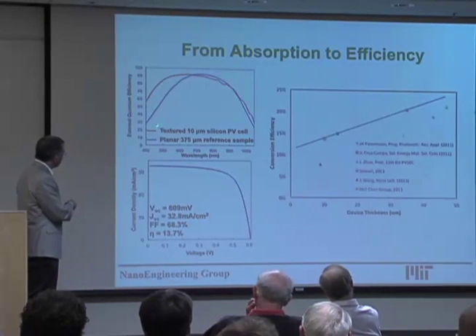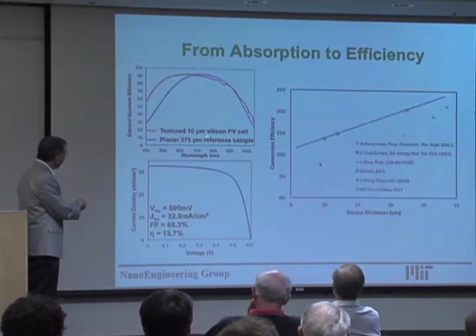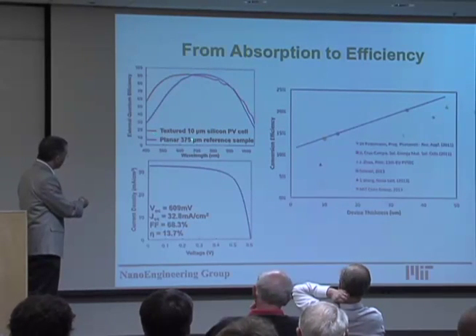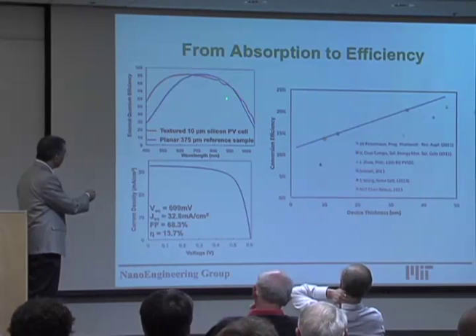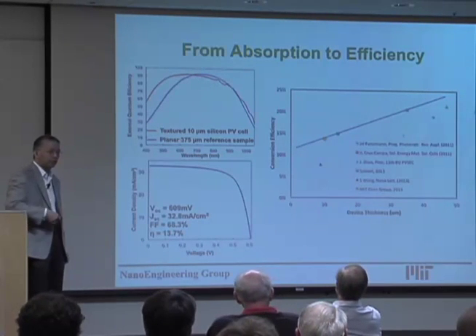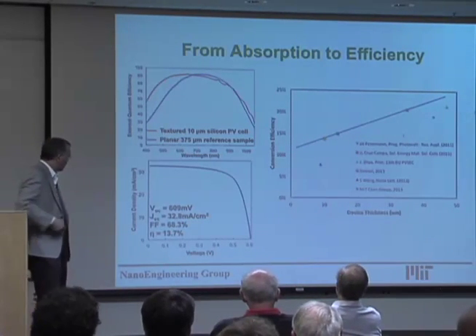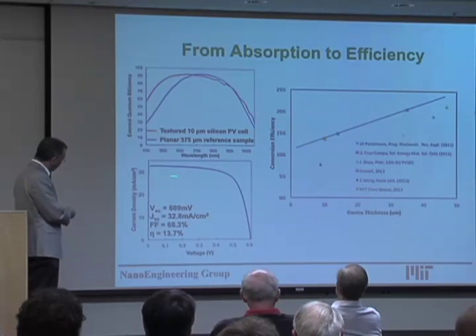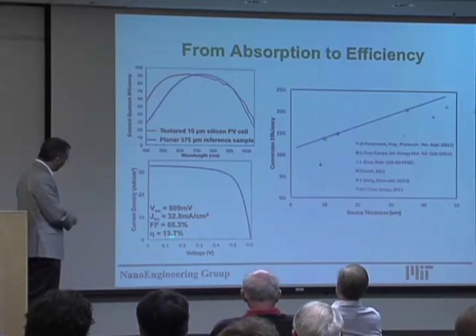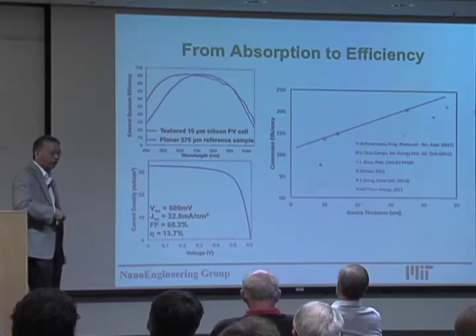So here is the absorption of a 10 micron silicon cell versus a 375 micron planar structure, and the absorption again could be comparable, better. And the cell so far we achieved is about 14% efficiency.